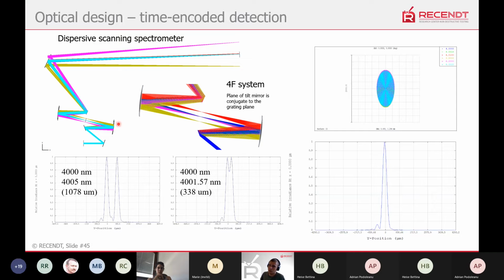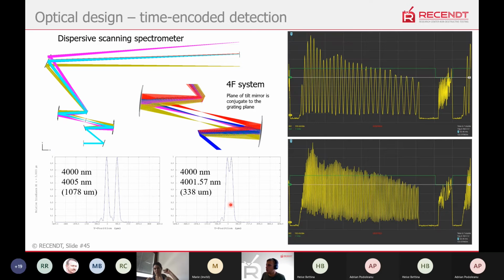Yeah, it can be corrected using toroidal optics and an already more advanced design, but this was built using off-the-shelf components. The resolution of the spectrometer is quite good. What we could access with optical design software is around 2 nanometers for a very broad range. The range is from 3.1 to 4.2 micrometers. And this is just how the signal looks like on the oscilloscope, close to the zero delay plane position and outside of it. One scan takes around 40 milliseconds, I think.